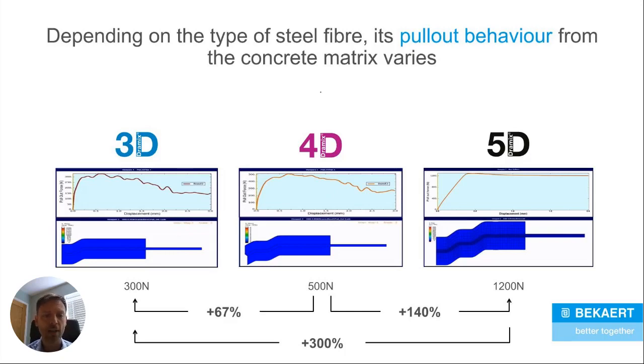Dramix 4D was developed after a 3-year research and development program between 2009 and 2012. And you can see the failure mode is actually very similar to that of the 3D fibre, but you actually need a much higher force to start that elongation of the anchor. So 500 newtons to see the fibre start to pull out of the concrete. So the 4D fibre has the same failure mechanism, but it takes a greater force for it to actually happen.